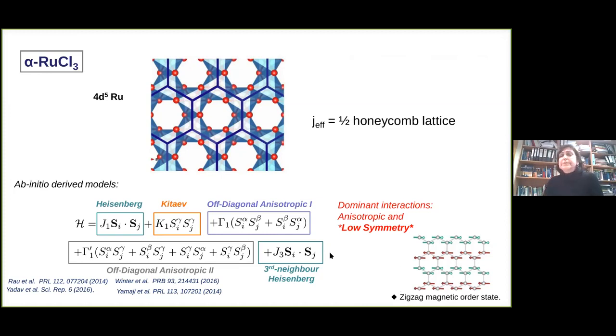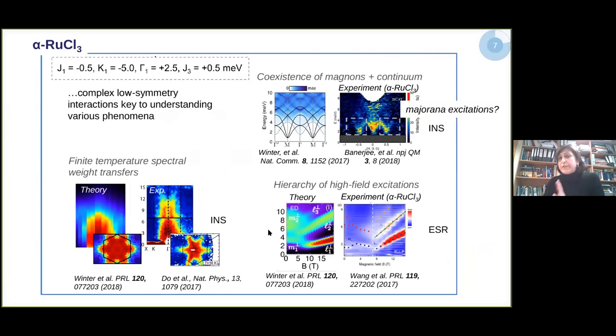And in order to convince you that the description of this system is not only Kitaev, but also these other anisotropic interactions, let me just flash here some experimental measurements on these materials. So on the right, I'm showing the experimental measurements. So this is, for instance, inelastic neutron scattering experiments on the ordered phase, where one nicely sees these magnon excitations due to the ordered phase, but there is a very strong region of continua of excitations, which is not present in a typical Heisenberg-like material.